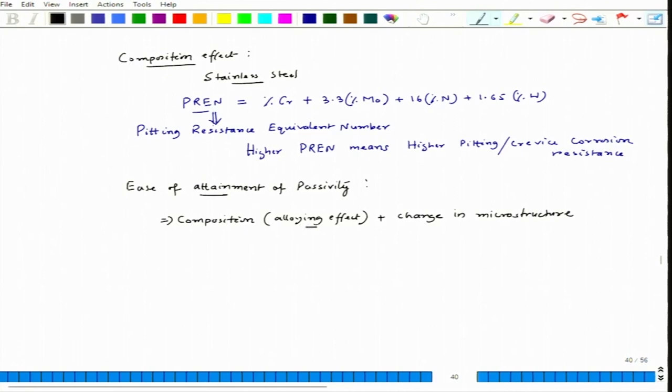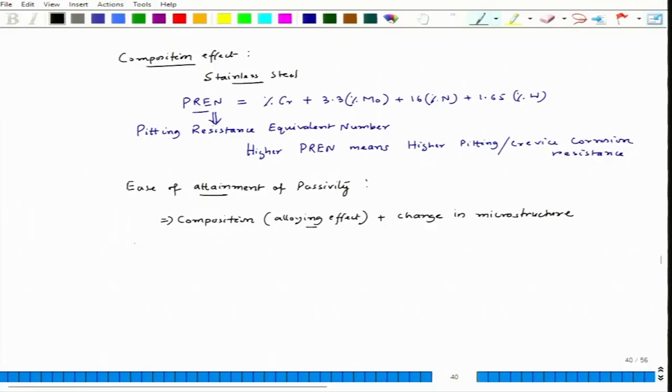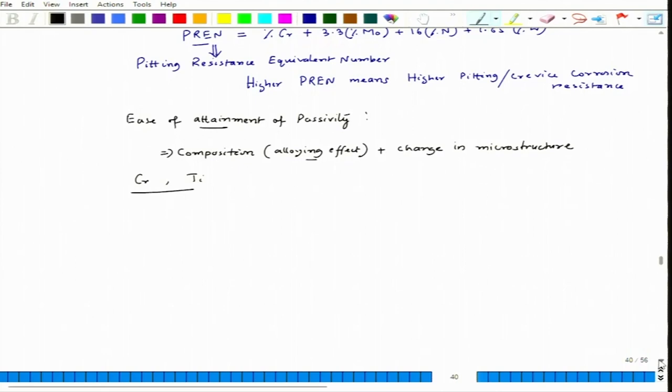The choice of alloying element is decided based on the alloy system we are considering, since we are looking at passivity. For example, in case of chromium or titanium, if we add a little platinum or palladium we can get spontaneous passivity. This applies when there is hydrogen ion reduction but no strong oxidants present — strong oxidants include dissolved oxygen, ferric chloride, or Fe³⁺. Chromium and titanium are chosen because both show active-passive behavior.